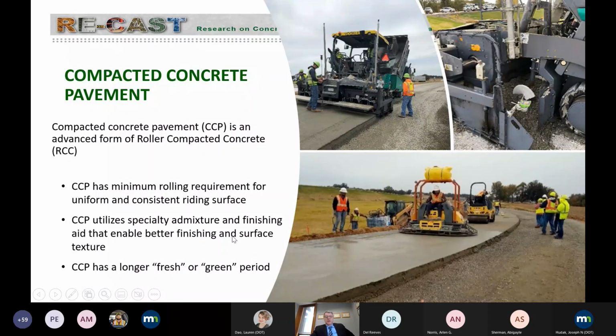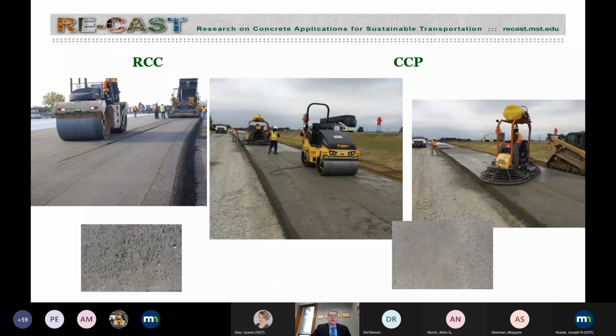The technology of CCP uses proprietary admixtures. There are two admixtures that are used. One of them is used in the mixture composition itself. Another one, what you see over there, that blue liquid, is used as a finishing aid. And because of the admixtures and the finishing aid, the concrete itself tends to have a longer workability retention, allowing longer time for consolidation and finishing.